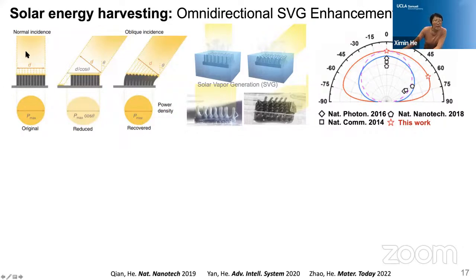For example, when the light shines on the surface at a normal incidence, you will have this smallest projected area so that you have the maximum power density perceived by the surface. But if you shine the light at an oblique angle, then you will have an enlarged projected area. So it basically dilutes this perceived light intensity, and then you basically lose some energy. But if we can engineer this surface with a forest of little sunflower pillars on the surface, then maybe all these real-time light tracking pillars can always restore this minimum projected area to maximize this light harvesting power density.